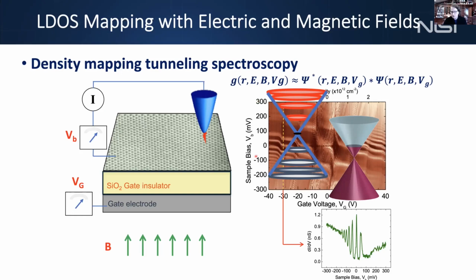So in this talk, I'll show you a number of these maps, and we'll pick out 2 of the variables at a time. So this was energy versus gate voltage, but I can also fix, for example, the gate voltage and plot as a function of distance, or I can fix the distance and plot as a function of magnetic field. We'll see all 3 of those combinations, so it's important to examine. I'll point out what is being plotted so you understand what we're probing. So this is really LDOS mapping in this fourfold manifold of space.